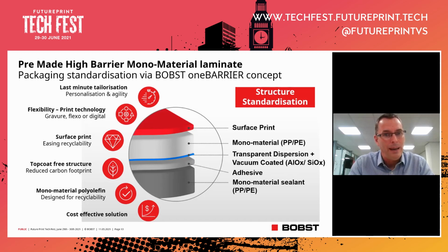That pre-made laminate can then be last minute tailored with the relevant surface print technology selected when needed for the application. So beyond just the standardization of the pre-made high barrier laminate concept, it also offers many benefits, and I'd like to try and focus on a few of these more important benefits. The first thing for me is barrier performance. The barrier package concept is based upon wet dispersion coating, not co-extrusion, and also dry vacuum coating to provide two very thin but complementary transparent high barrier layers.